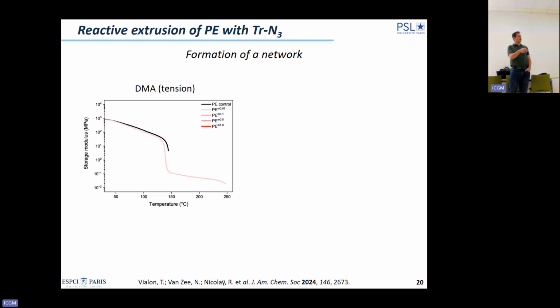And now, if we add a bit of additive, 0.05 mole%, so this is really not a lot, this is 0.5 weight%, you start to see, you can measure the storage modulus, and if you increase the loading, you have a storage modulus which is increasing, which we expect when you cross-link the material. The value of E prime on the rubbery plateau, if it's homogeneous, should be proportional to the cross-linking density. And in our case, we reach a plateau: if we double the amount of additive from 0.5 mole% to 1 mole%, we don't see any change in the storage modulus.